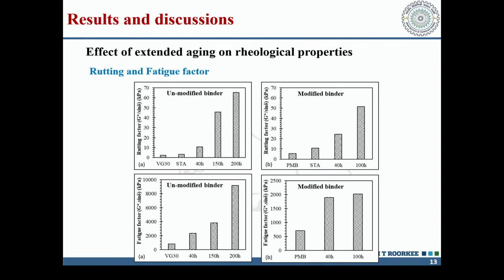So you can see here rutting and fatigue factor. Rutting factor is G star upon sine delta, and fatigue factor is G star into sine delta. And these values are shown here. And you can see here that the value of G star upon sine delta is more for the modified binder, which means that it is better in that case. And for the fatigue factor, you will find again it is less because it should be less. So for modified binder, fatigue factor is less.